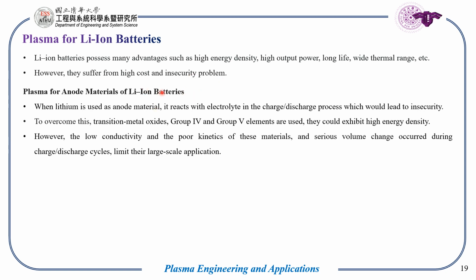When we talk about lithium-ion batteries, we consider the anode materials, which are the most important part in those batteries. When lithium is used as anode material, it reacts with the electrolyte during the charge and discharge process, which leads to the insecurity. When it is used for a long time, it gets more heated up, and those heating issues can cause, and may even lead to, blasting of the batteries.